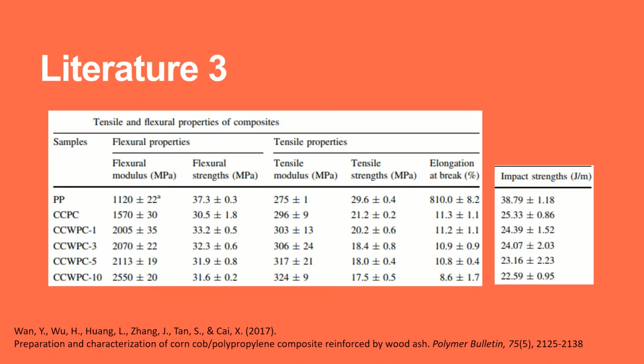An interesting application of corn cob and polypropylene was performed by Wan et al. in 2017, where the researchers investigated the mechanical, morphological, as well as thermal properties of corn cob flour, wood ash, and polypropylene composite. In this publication, maleic anhydride grafted polypropylene was used as a compatibilizer to improve the interaction between the fillers and the polypropylene. Results shown in the table clearly demonstrated the effects of varying amounts of corn cob flour and wood ash loads on the mechanical properties of composites. The conclusion could be drawn as following.